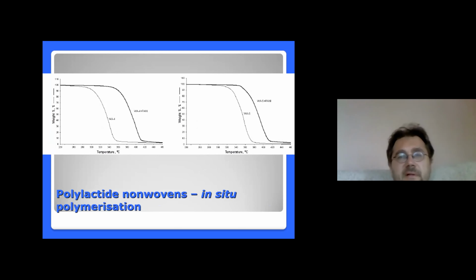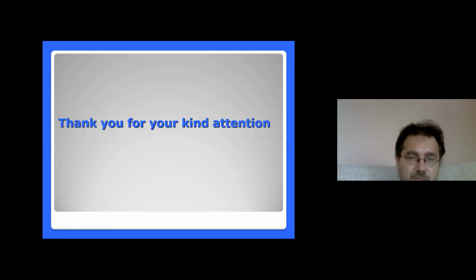Okay, and the last property which I would like to show you. So we can change the hydrophilicity during the surface modification, we can make electric conductivity, and even we can change the thermal resistance of the material, because the deposition of different number of layers can increase the thermal stability. What was a little surprising, because the thermal properties are not surface properties, they are volumetric properties, but it appeared that with this very delicate surface modification we can change even thermal properties. So it was something surprising.